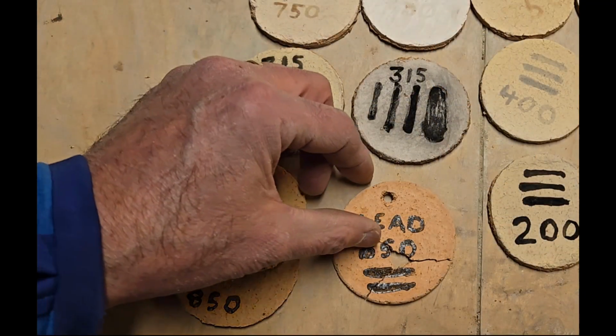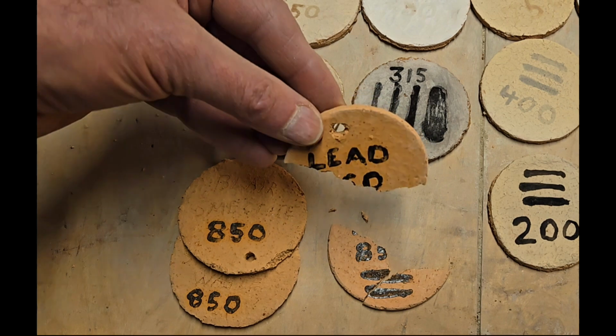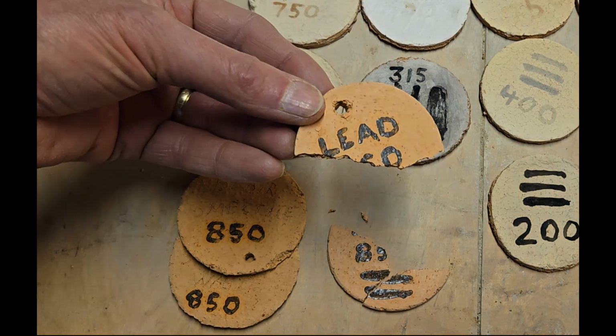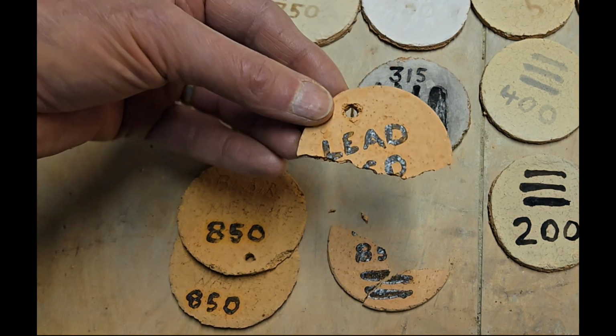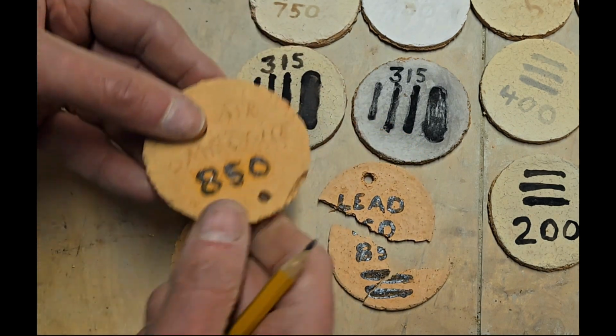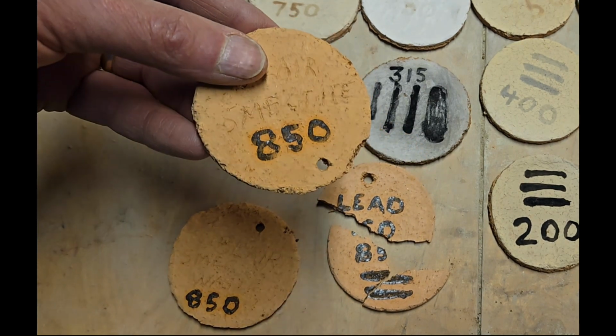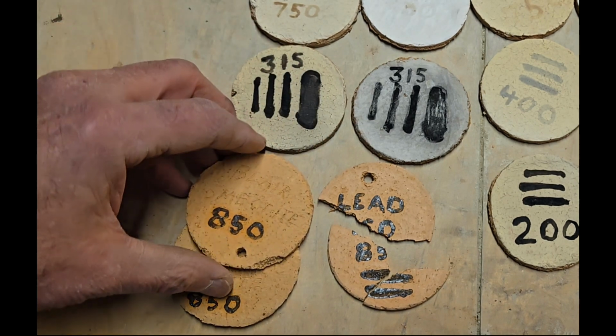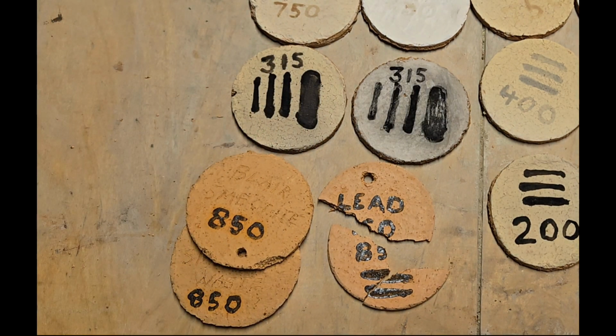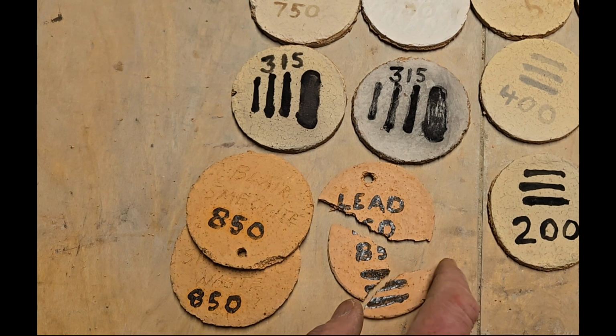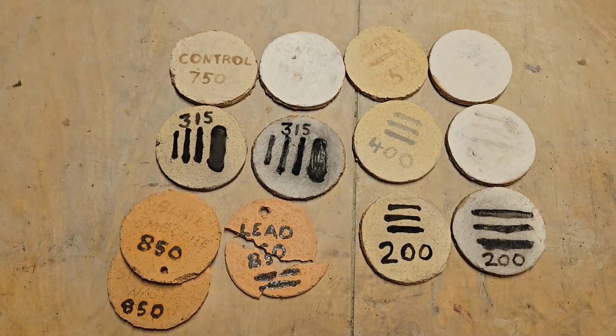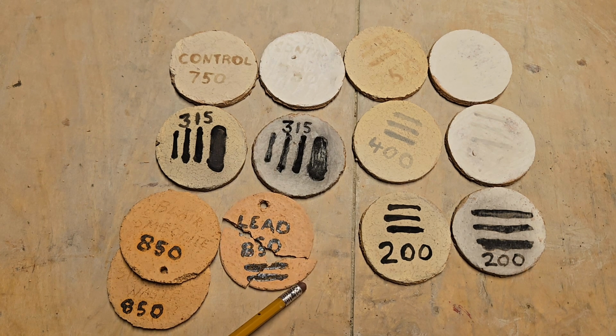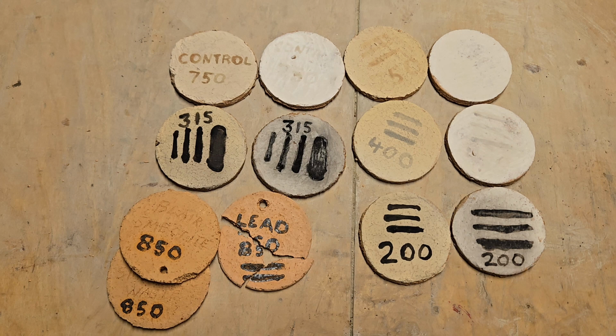But this is probably the best indication of a glaze. This was a lead paint that had some other minerals added to it. These are some other tiles where I just wrote 850, and you can see there's glaze to that as well. So it has lead paint and/or lead ore, copper carbonate, manganese, and some clay to get it all to stick. So that's what the research in the journals would say, is that this paint had a high component of lead. Good experiment, more to be done, but always useful to do these kinds of experiments.